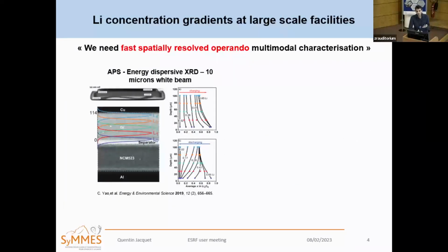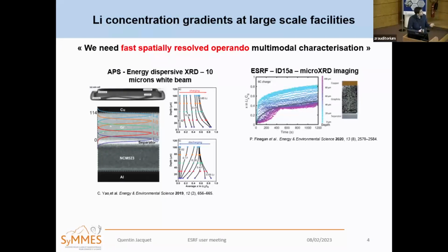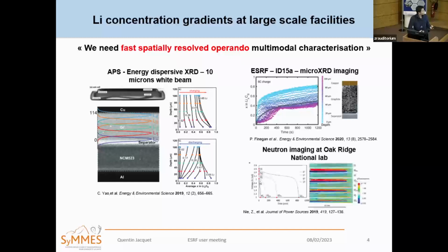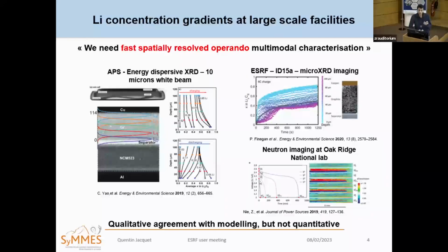Obviously, when we think about fast and spatially resolved, we think about large-scale facilities, and there are a few beautiful examples in the literature on how you can look at concentration gradients in batteries. So at the APS, for example, where they studied both graphite and NMC materials. Examples at the ESRF on ID15A, where they look at very fast charging in the presence of lithium plating, or examples for neutron imaging, for example, in Oak Ridge. And these beautiful experiments give us a qualitative insight on mechanisms, but from the authors themselves, it is still not quantitative when comparing to modeling, which means that we're still limited in our capability of predicting the performance of these batteries using modeling.